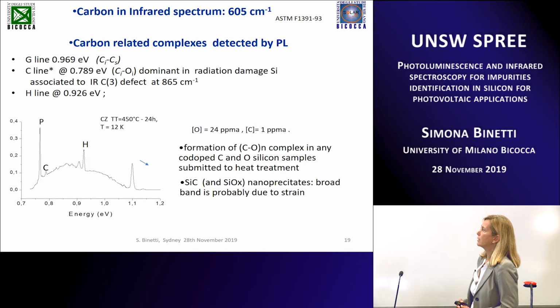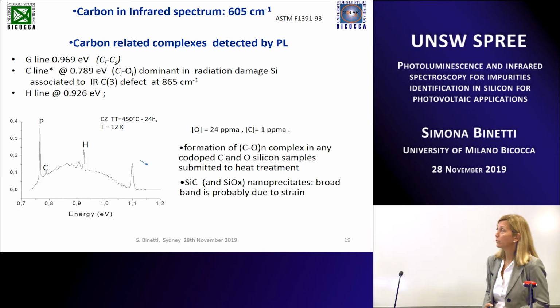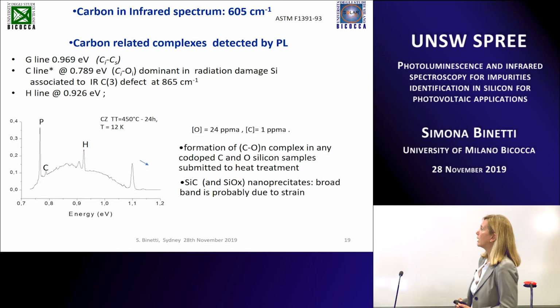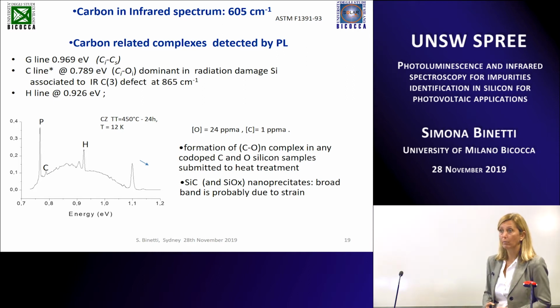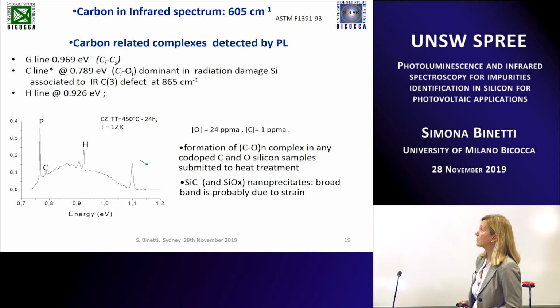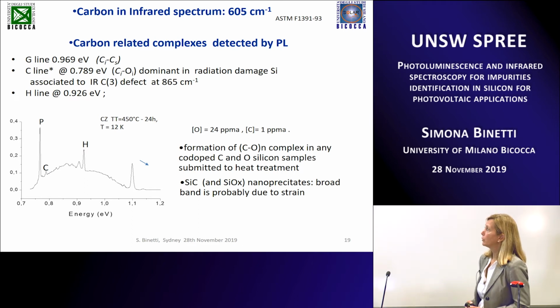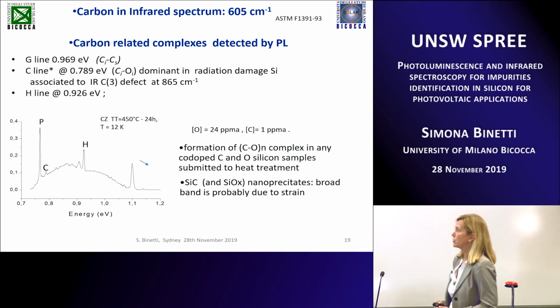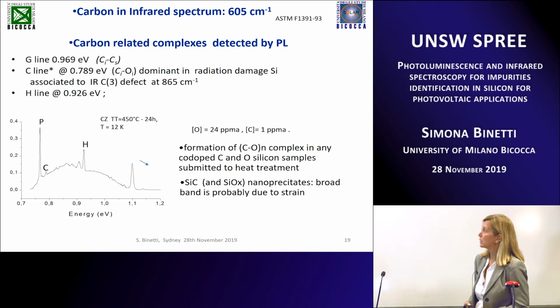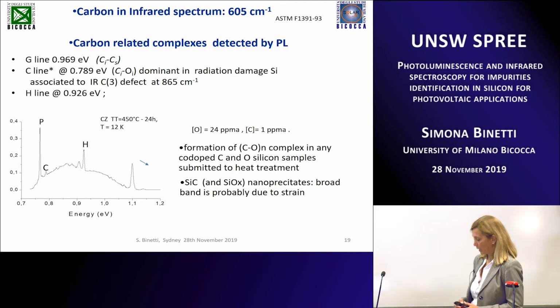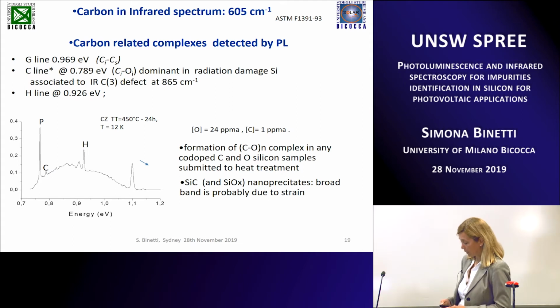And we have seen that after a thermal treatment at 450 degrees C for a long time, we detected the C line, the H line, and the P line, lines that are related to the formation of carbon and oxygen complexes. The broad band that you can see has been associated with silicon carbide and silicon oxide nanoprecipitates that can induce strain and are responsible for this broad band, and we will see this later.